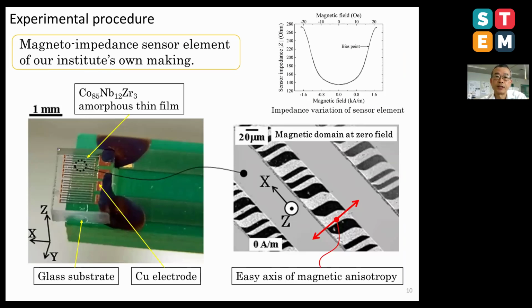This sheet shows the sensor element, the simple magnetic impedance sensor, and the driving electric circuit, which was our institute's own making. The sensor was made of an amorphous cobalt-niobium-zirconium soft magnetic thin film, having an easy axis of magnetic anisotropy in the width direction of the element.